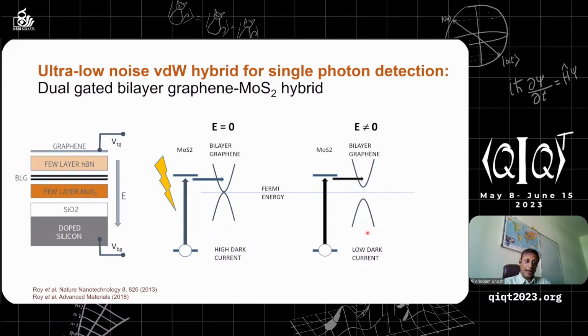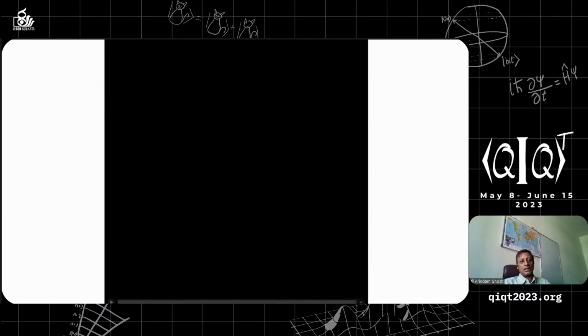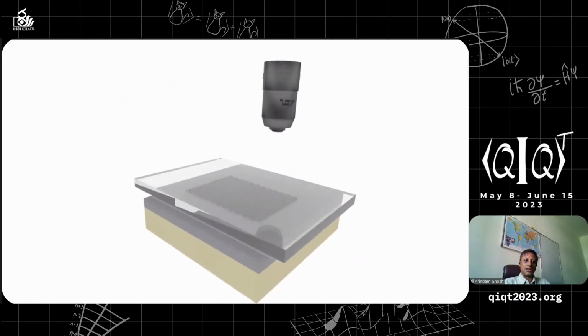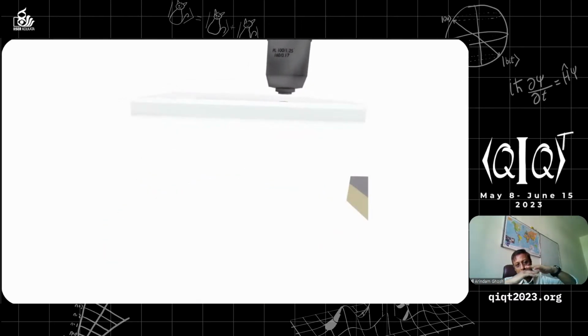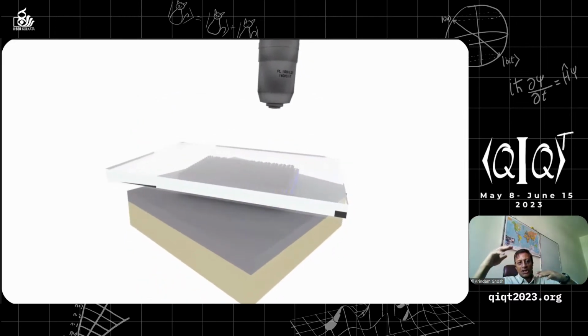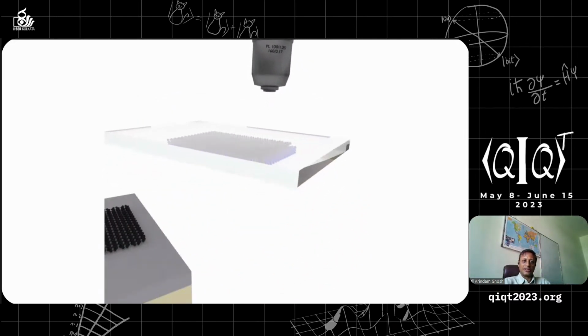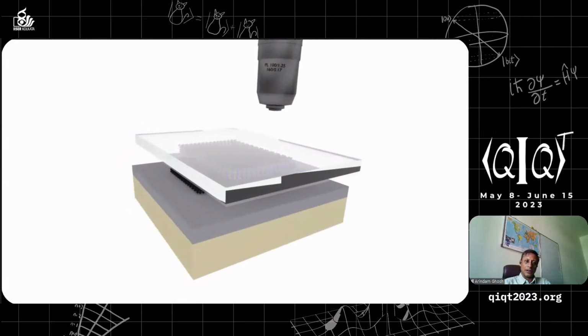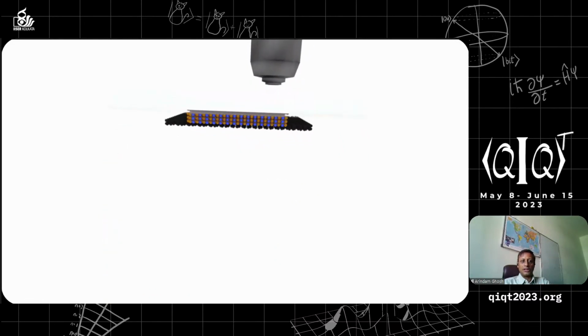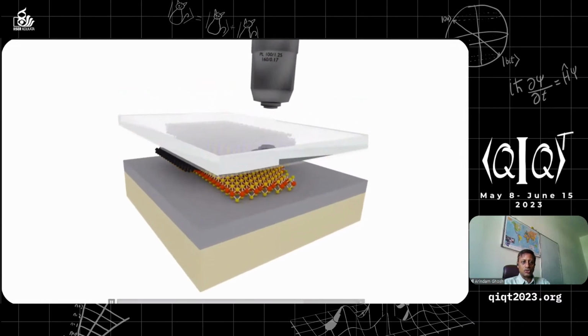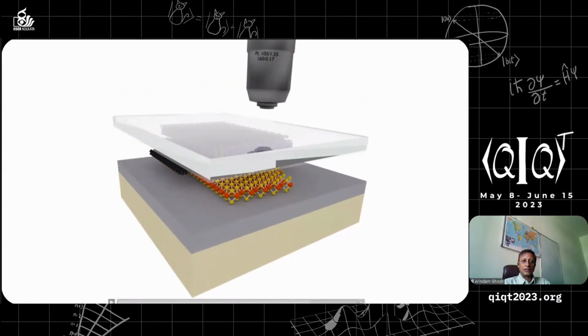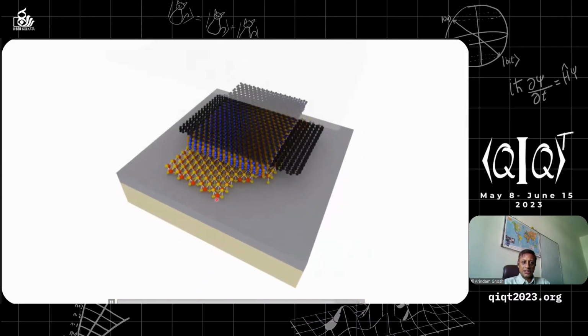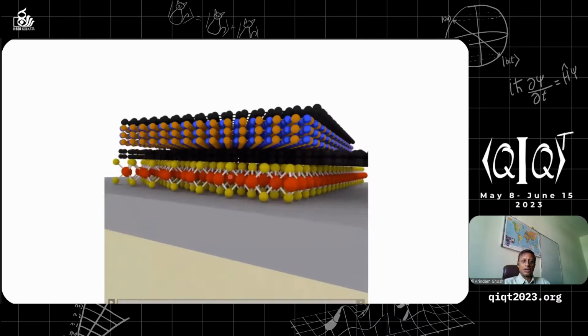By the way, I'm showing these cartoons, but these are complex devices to make, and this is usually called van der Waals heterostructuring, which is used in many of our material engineering strategies, in which you take materials layer by layer and put them on top of each other in a sequence that we want. For example, here is how the bilayer graphene MoS2 photodetector was created. This is a layer of MoS2. This is molybdenum disulfide and the bilayer graphene on top.